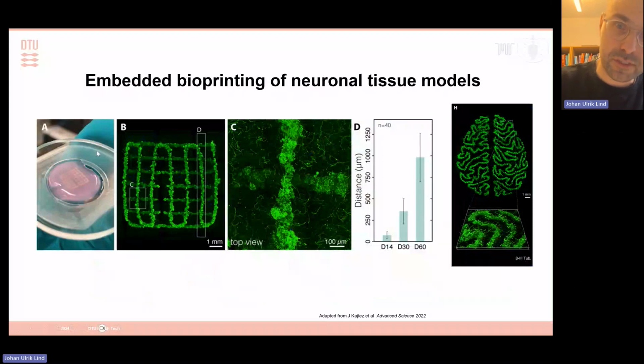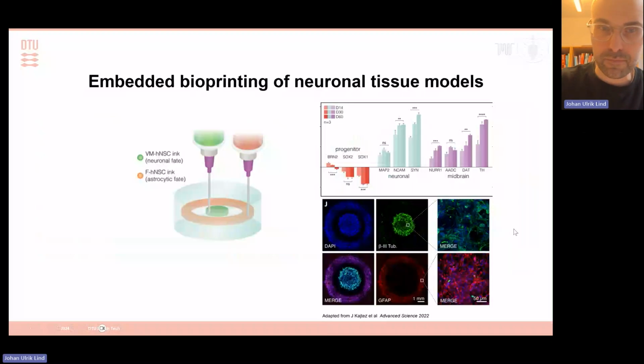But what's interesting, of course, is when we're now printing in these composites of alginate and collagen, where about 1/3 of the volume is essentially a collagen-based matrix, we can see cellular outgrowth, and we can have axons that grow up to millimeter distances from where they are printed. That means that we can start compartmentalizing, printing different types of neuronal tissue, and have connections being formed in situ between those, in a soft environment that mimics the native brain, you could say.